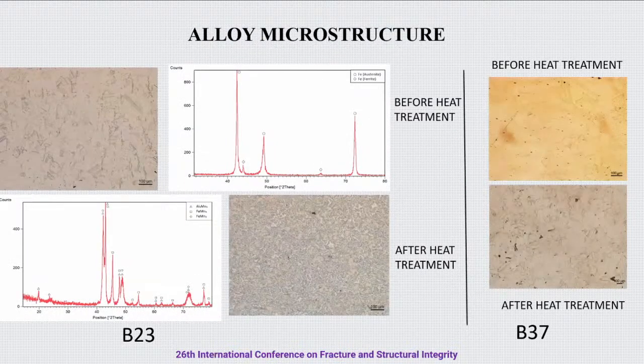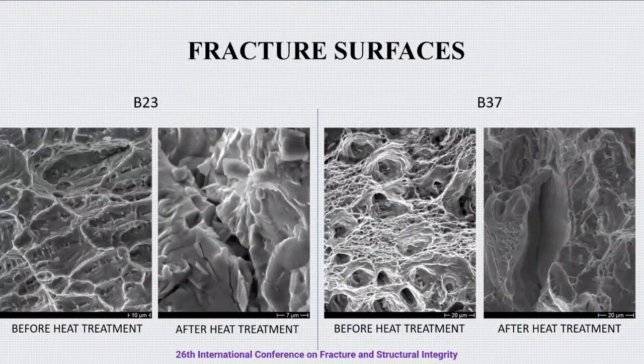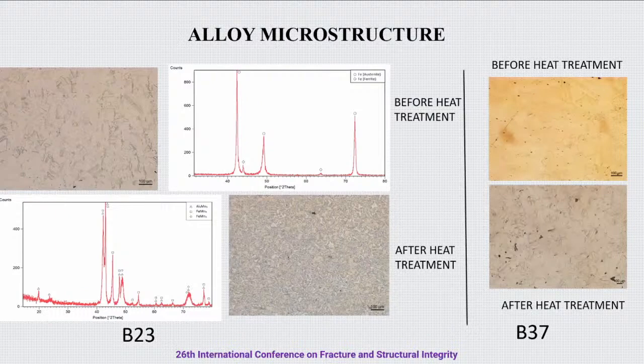The next thing is the alloy microstructure. For B37, before and after heat treatment, the microstructure did not change. It had an austenitic structure. B23 shows a change in its microstructure. Before the heat treatment, it has a microstructure similar to austenitic steel, which is verified by the XRD graphs. But after heat treatment, we see the formation of intermetallic phases of aluminium, manganese, and iron manganese, which is again verified by the XRD graphs.